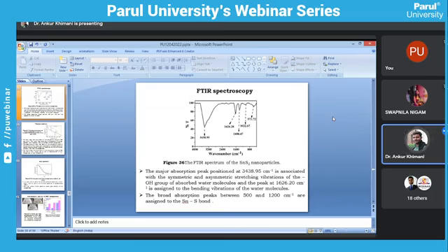FTIR spectroscopy. The major absorption peak at 3438.95 centimeter inverse is associated with the symmetric and asymmetric stretching vibration of the OH group observed in water molecules, and the peak at 1626.20 centimeter inverse is assigned to the bending vibration of the water molecules. Over here, this big peak is because of the water molecule. And the broad absorption peak, 500 to 1200 centimeter inverse, is assigned to SnS2. So the metal peaks are observed over here.